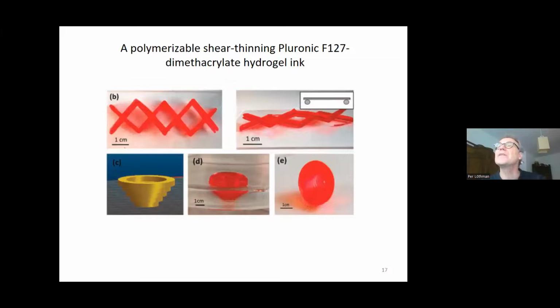Here we have another experiment, an example of a polymerizable shear thinning pluronic hydrogel ink, which was mixed with an initiator, persulfate. It was printed upon a supporting catalyst bath, as you can see here in the middle. After removal from the bath, in the pictures below, D and E, complex printed structures such as an inverted cone retain their shape without collapsing. And this is much due to the polymerizable shear thinning pluronic dimethacrylate.